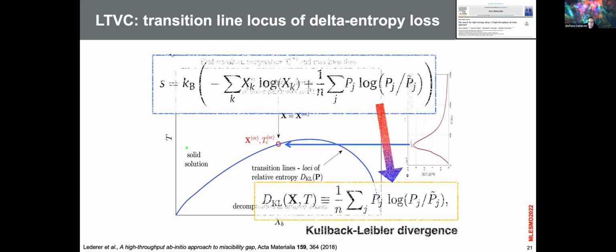If you do this, and you put this definition back inside, you find that this change of entropy is exactly the Kullback-Leibler divergence, which is the population vector of the entropy above divided by the population vector of the entropy below. This is very important because this Kullback-Leibler divergence does not measure entropy. It can go to zero. It measures the relative loss of entropy. You say, I lost 50%. I lost 20%. So you can really go to zero, because at zero temperature there is no entropy. But you can say that in the limit, you lose 50% of epsilon. So you do not violate the second law of thermodynamics, that there is no entropy at zero temperature.